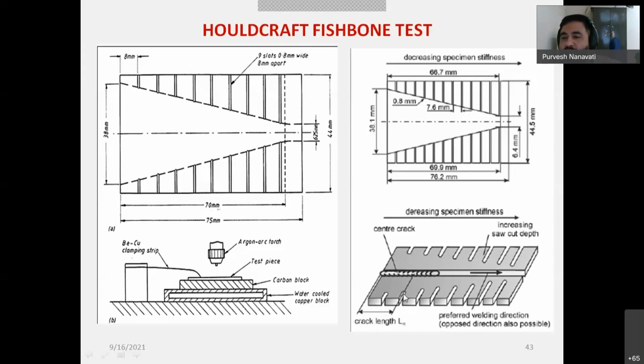Now you start your welding from over here. This is your welding direction, right? This is the preferred welding direction. You are moving toward an area where you have a high saw cut depth, or a minimum area. Putting it another way, you have less material available to throw the heat. It means when you are moving your heat source from this end to this end, your heat should get dissipated through the plate. Are you agree with this? Your moving heat source should get dissipated through the thickness. Now the thickness or the volume available here is very less. You have no volume available here because of this cut length, because of this cut, because of this vacuum, because of this non-availability of the material. So what will happen?